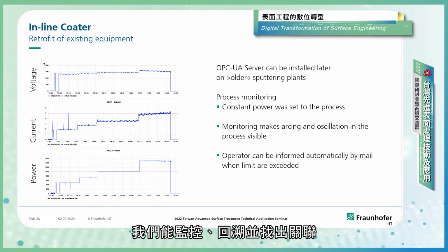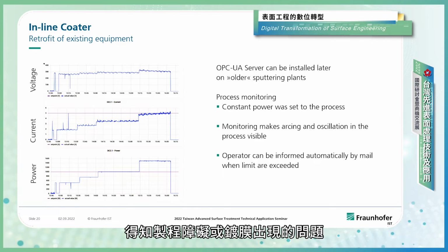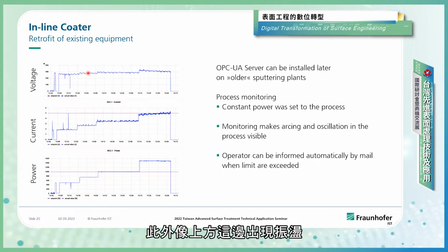We can monitor, we can trace back, and also correlate if there is some failure, if there are some issues in the coating. Furthermore, you can see some oscillations on top of that, which is correlated to substrate movement, since our coating source is a cylindrical cathode, a tube that is rotating, and if there is uneven rotation, you see some deviation in the current and voltage signal. All this information you get, and you can collect and improve your process with that.